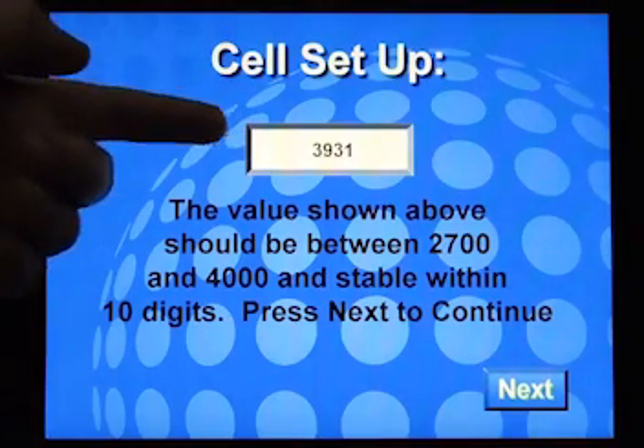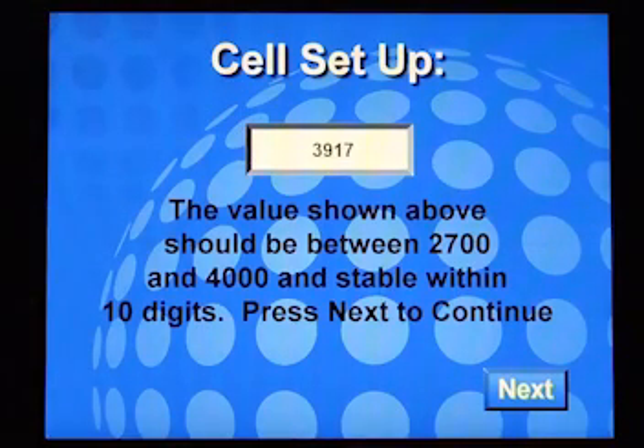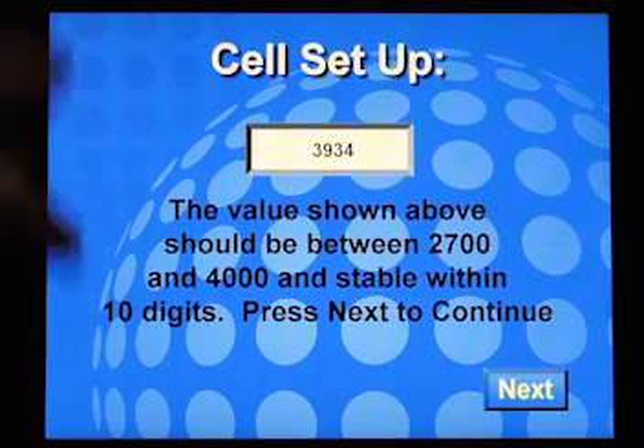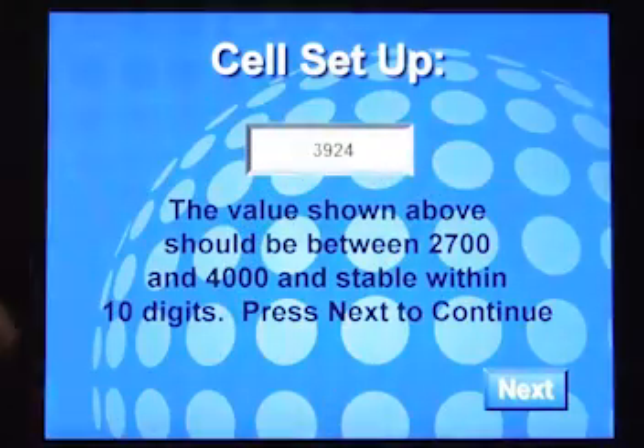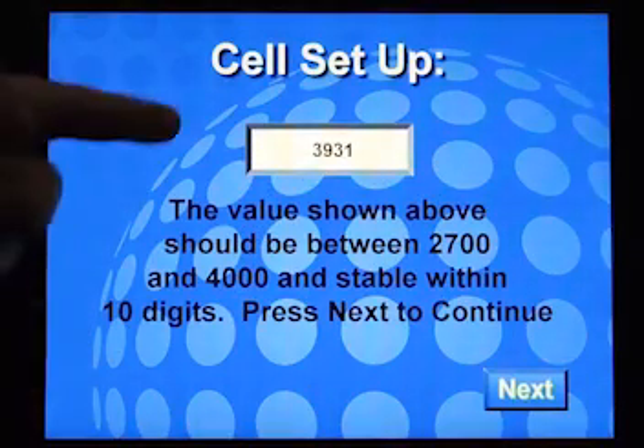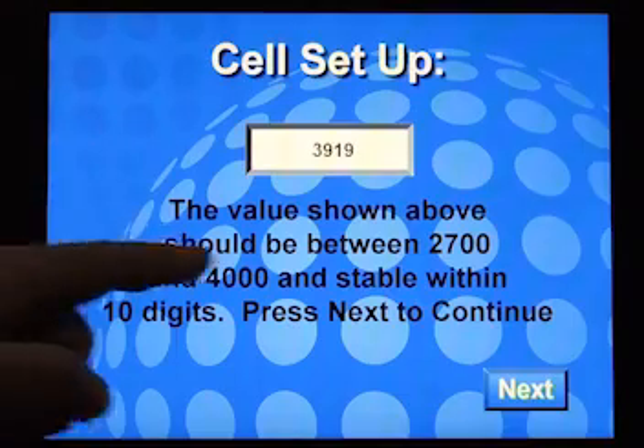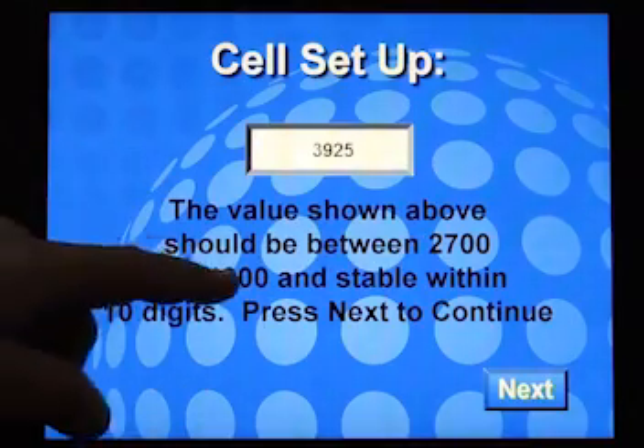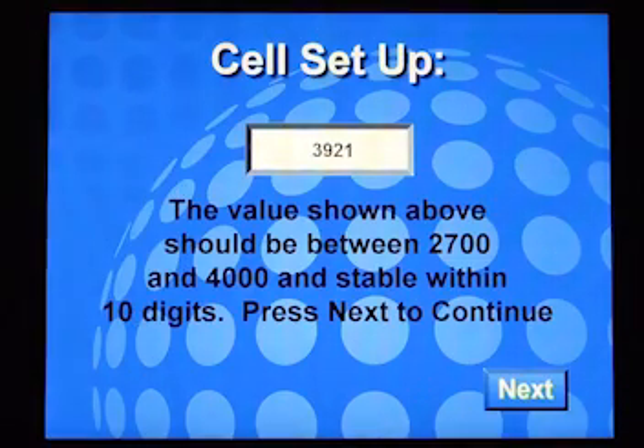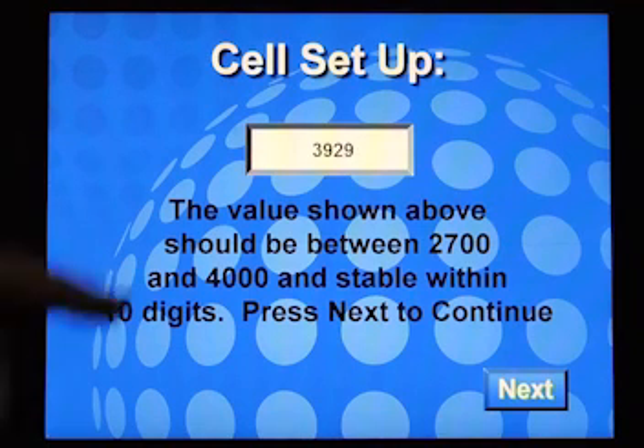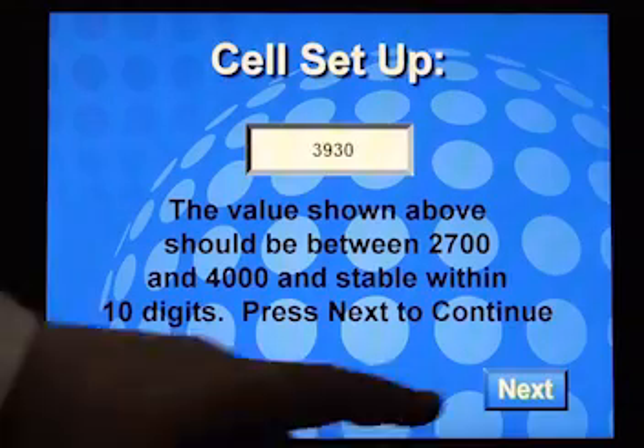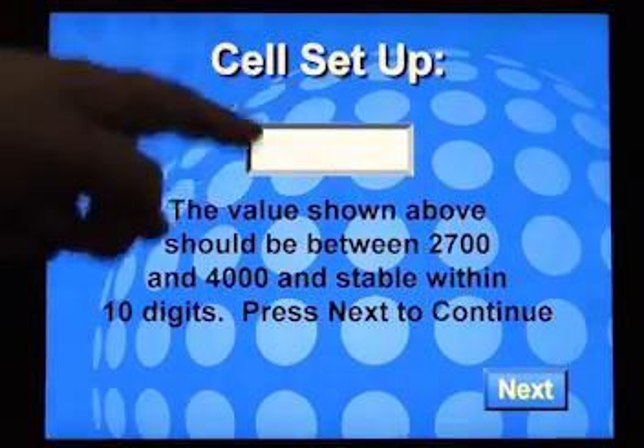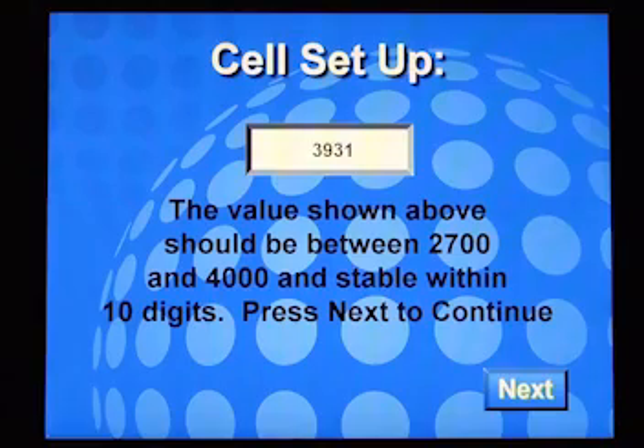The system will use this number to determine 100% transparency. You can move the cell slightly left or right to maximize this number. The number should be between 2700 and 4000 and stable within 10 digits. At this time, it is best to leave the system 5 to 10 minutes to stabilize. When the difference is less than 10 digits, press Next. The system will regard the final number as 100% transparency.